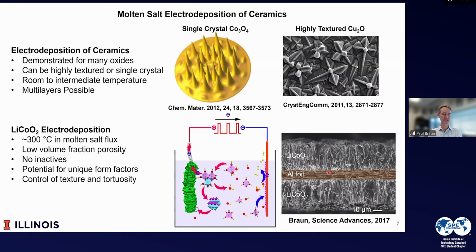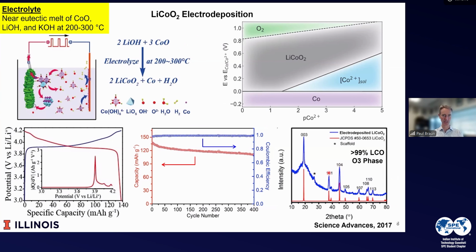So what is the physics and what is the chemistry? So in the specific system that we work on, which is lithium cobalt oxide, and I'll mention a few others as we go through, we have to look at the Pourbaix diagram. The Pourbaix diagram gives us an idea of what is stable, at what potential and concentration. And what we see is that there is a stable electrochemical region of lithium cobalt oxide. And the process here is that we dissolve the cobalt oxide in a near eutectic melt of lithium and potassium hydroxide. Then we electrolyze, we oxidize the cobalt from 2+ to 3+. And when we do the oxidation, it precipitates as lithium cobalt oxide. At the counter electrode, we deposit cobalt and then produce water, which boils out of the bath.